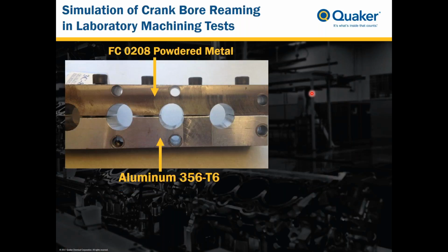So what we did is we developed a workpiece that simulates the actual crankshaft bore, and this is shown in the picture on this slide. We fabricated it out of two materials: aluminum 356-T6, which actually simulates the engine block, the lower half of the bore, and then the top half is fabricated out of a sintered powder metal, FC0208. This material is a very common powdered metal that's used for main bearing caps in automotive production.